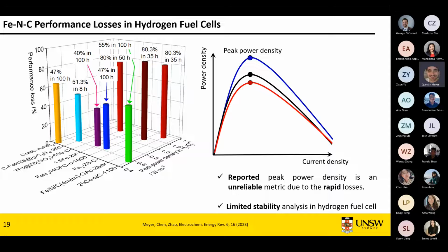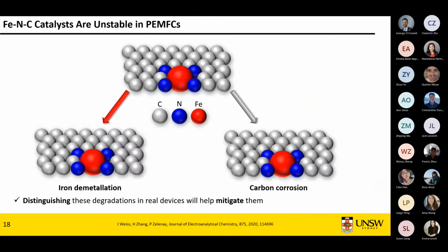So it's quite difficult to analyze it in fuel cells, mostly because you have processes where you lose 20% of performance in 5 to 10 hours. So it's difficult to select a method to characterize it properly. There is still a good understanding of what's happening, even if we're not sure quite how it happens. There are two main mechanisms that can kill your catalyst. First one is simply iron demetallation. So your iron nitrogen carbon active site is not quite stable. It's going to leach out of your structure. That's the first problem you've got.